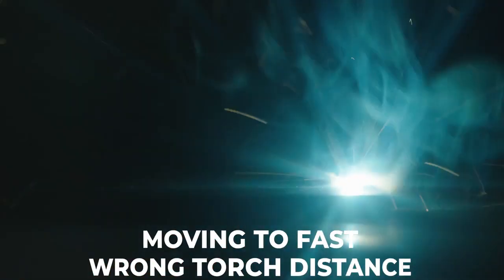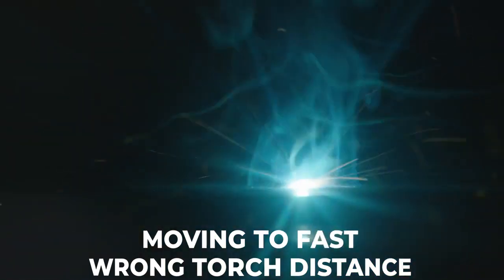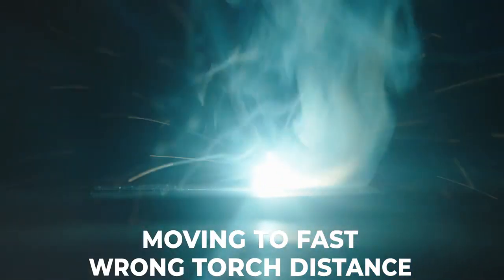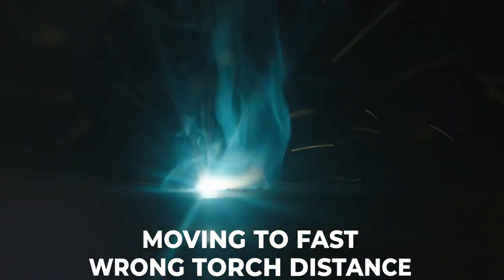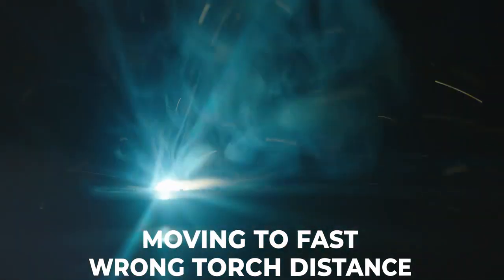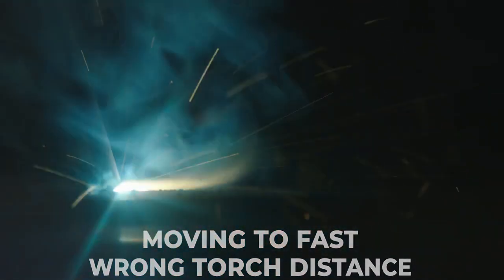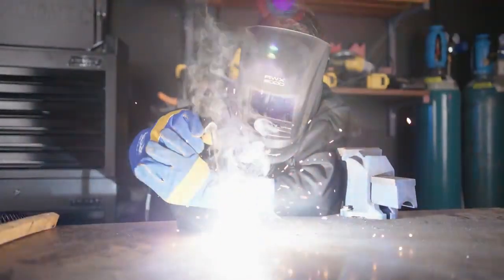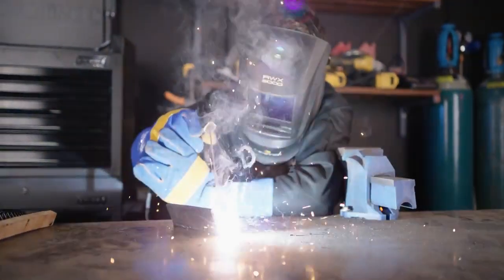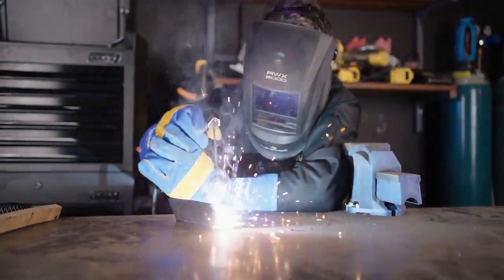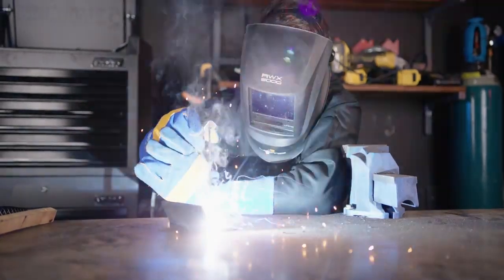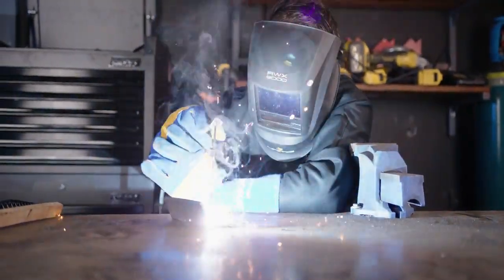If your arc is too short, then you're going to lower the voltage and the weld pool will become cooler, resulting in a non-penetrating weld. This also has a potential to extinguish the arc. If your arc is too long, then the voltage will increase, more spatter will occur, the arc will become erratic and unfocused, and this also has a potential to extinguish your arc. When you're first learning to stick weld, keeping a tight arc can be tricky, so make sure to get comfortable, lean on something if you must, to keep a steady hand.